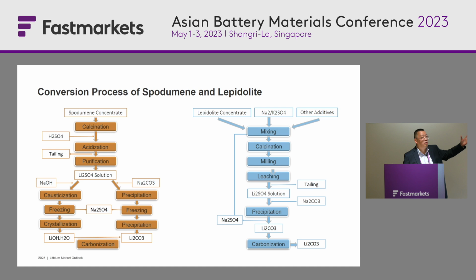And also, you add some additives. These additives try to lock in the fluoride in the mine and something like that. Okay, so these additives, and they mix it together. And then calcinating it, and the calcinating temperature is a little bit lower than 900 degrees compared to the spodumene concentrate, which is over 1,100 degrees. So they have lower calcination temperature.